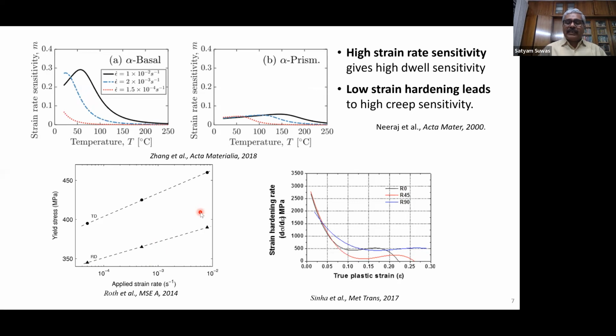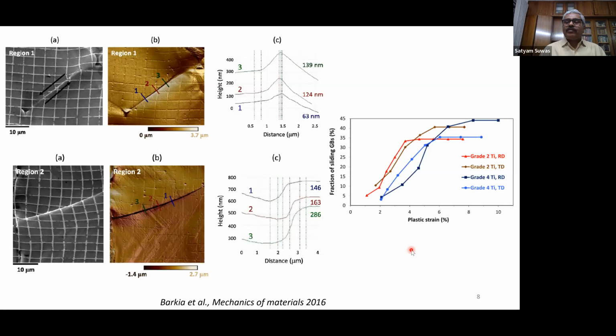Also, the strain hardening rate in titanium is sensitive to the direction in which we take the sample. Again, it's a function of texture. So we can see that along the rolling direction, at 45° to the rolling direction and at 90° to the rolling direction, we have different responses of strain hardening rate versus true plastic strain. Now, we wanted to examine one by one many reasons that would lead to this dwell fatigue response, so that one after other some remedial can be recommended for this material. So the first thing is in-plane anisotropy. That is one that we wanted to see.